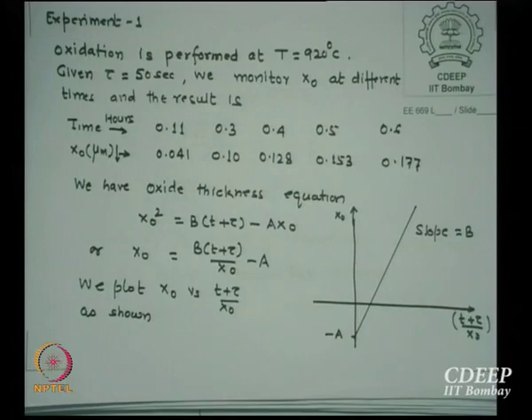So I could get B and B by A, that is KP and KL, if I know actual oxide thicknesses at different growth times. The assumption everywhere is that temperature is constant and also the mass flows are constant. So if I do the experiment, I will be able to measure B and B by A. And then what do I have to do? I have to repeat this for many temperatures, to get B and B by A dependence on temperature.